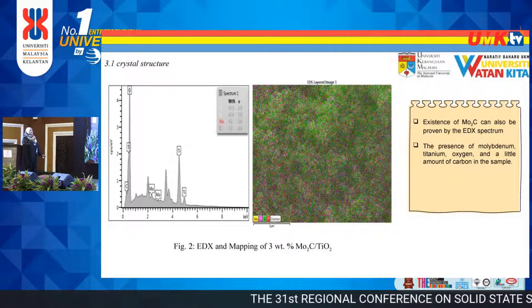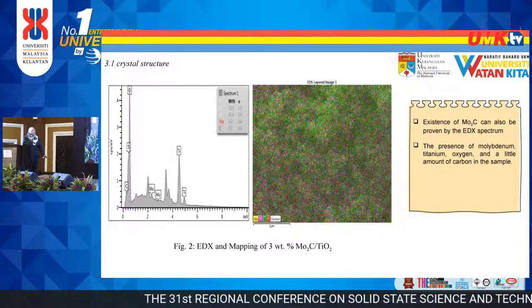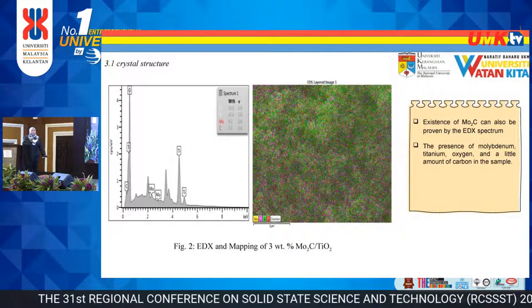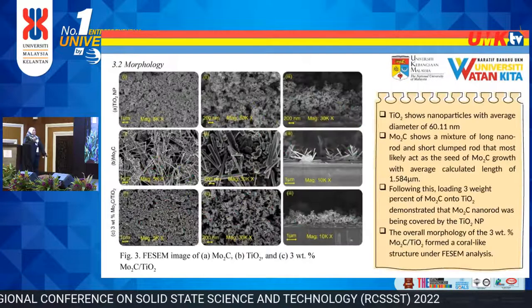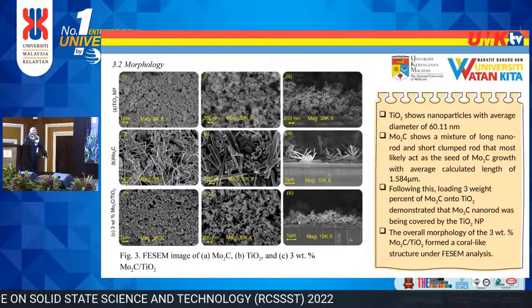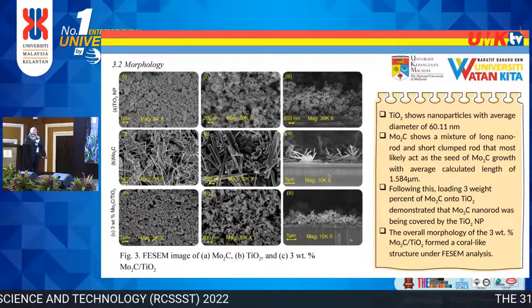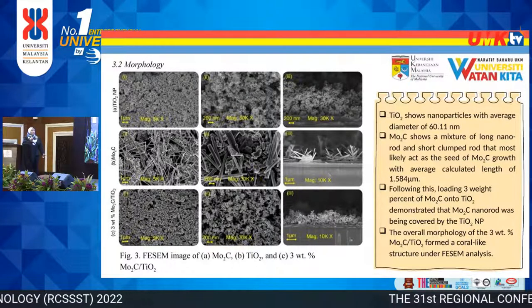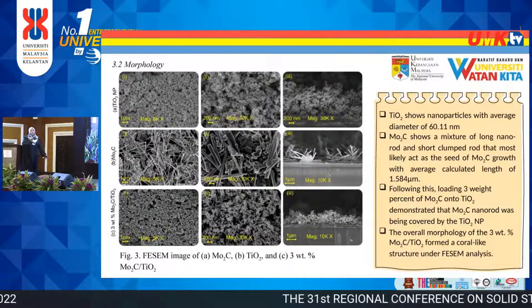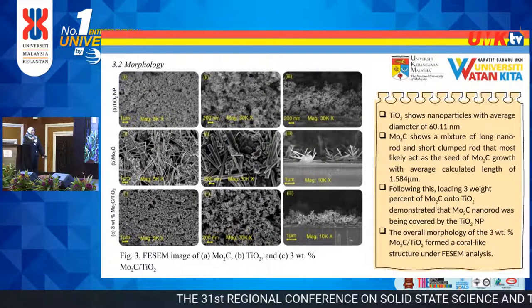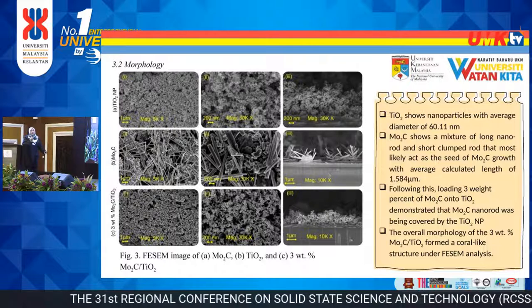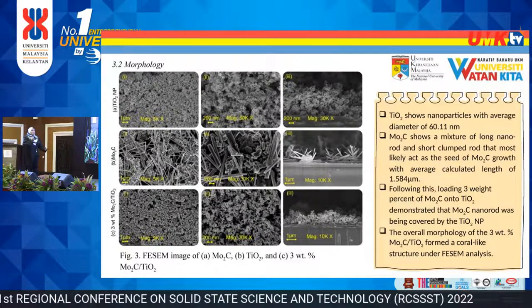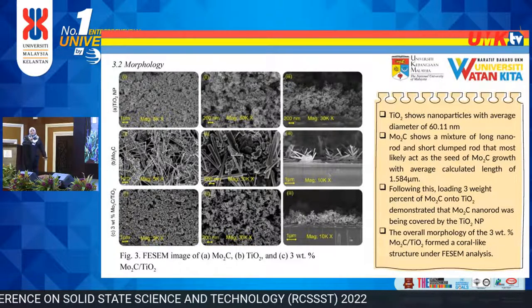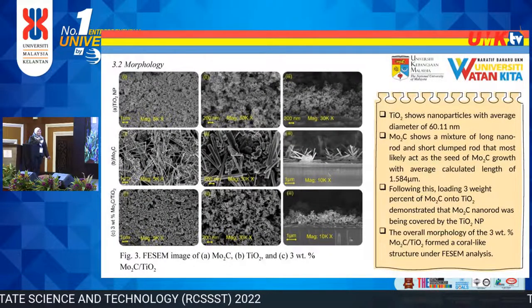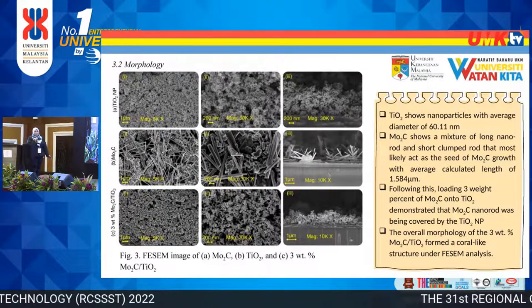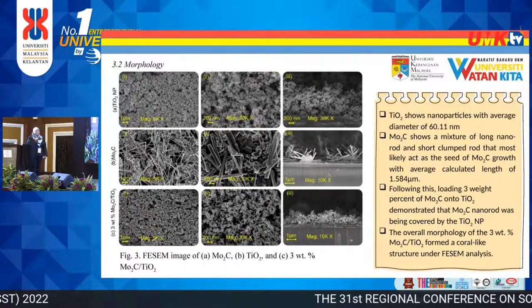From figure 3A, we can see that TiO2 shows nanoparticle size with the average diameter 60.1 nanometer, while molybdenum carbide shows a mixture of long nanorod and short clump rod, most likely at the seed of molybdenum carbide growth, with the average calculated length of 1.5 micrometer. After the loading of 3 weight% of molybdenum carbide onto the TiO2, it demonstrates that the molybdenum carbide nanorod was being covered by TiO2, and the overall morphology of the 3 weight% molybdenum carbide TiO2 forms a coral-like structure.